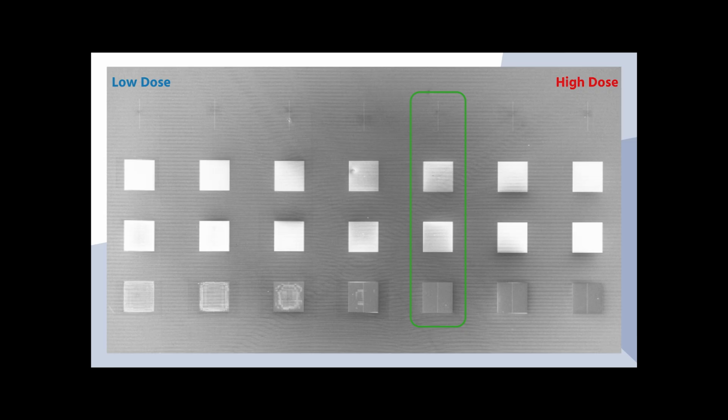The best dose is the tower pattern that works for all densities. Because you have tested the process at multiple densities, you know that the dose that you find using this method will work no matter what your pattern ultimately looks like. Do you have to use this method to determine your dose? No. You can test your process using your own pattern, but this is a more robust method for determining the optimal dose.